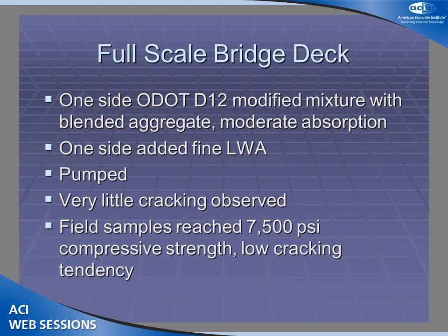So basically, in words, one side was a modified mixture using a blended aggregate. The other side, we added the lightweight aggregate. Both mixtures were pumped. Now, obviously, ODOT has no interest whatsoever in having a bridge deck crack simply to prove my point. And so we basically took a crack-resistant mixture, another one that was even more crack-resistant, and we really did not see much in the way of cracking. In fact, I'm not even sure we saw any at all.